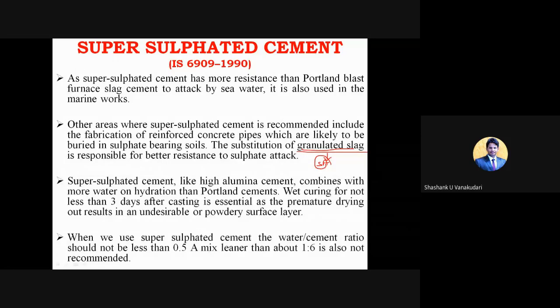When we use supersulfated cement, the water cement ratio should not be less than 0.5, because we need more workability and so require a larger water content. This is sufficient for usual concretes, but with supersulfated cement we should use a water cement ratio of more than 0.5. A mix leaner than about 1 to 6 is also not recommended, where 1 stands for cement and 6 for sand or other ingredients. A mix rich in sand is not feasible with this cement.